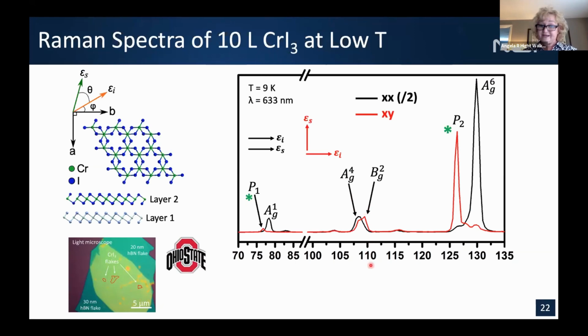Again, what's very nice about Raman spectroscopy is lattice configurations are easily spotted most of the time. And in this case, we can definitely see, using cross and parallel polarization, that we do see evidence of both the Ag and Bg, and those are only permitted in the monoclinic phase. So even up to 10 layers, where we thought we might be in the bulk approximation, we are seeing monoclinic.